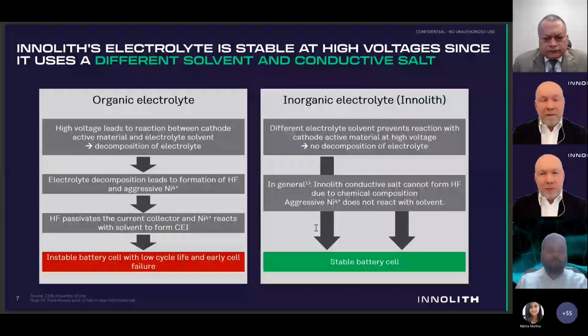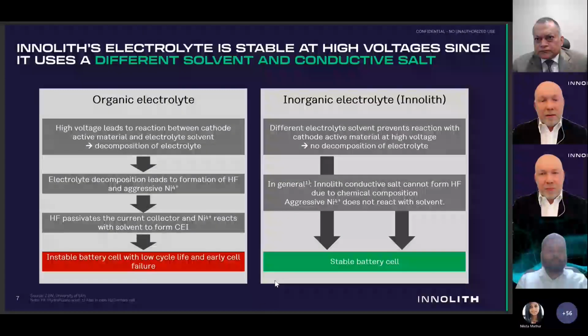And then HF attacks the cathode material backwards, and it also passivates on the current collector, and in the end we have very fast degradation of the cell. That's the reason conventional lithium-ion cannot be cycled at high voltages. Basically, cells cannot live any reasonable cycle life. With our electrolyte on the right side, you can see that it doesn't happen. There is no formation of HF, and it makes the system stable at high voltages.